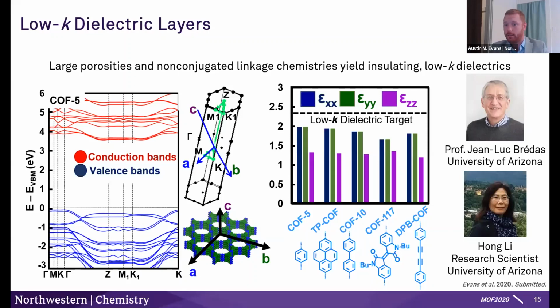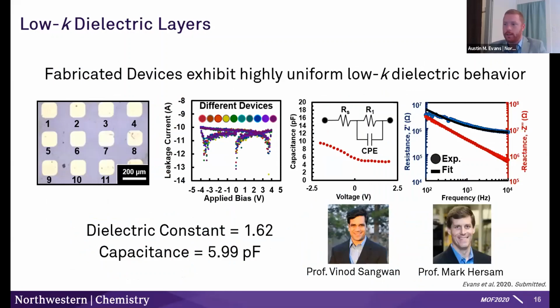So that's kind of an interesting property to investigate. And it's one that is relevant in devices, especially in atomically flat materials. So we decided to look into this experimentally, sort of inspired by those calculations. What you can do is deposit gold pads on top of this film, and you'll find that the leakage current is quite low across many devices. That's indicative that the film is highly uniform with no micro scale defects that would lead to shorting. I mean, you can see these pads are on the macro scale, hundreds of microns.